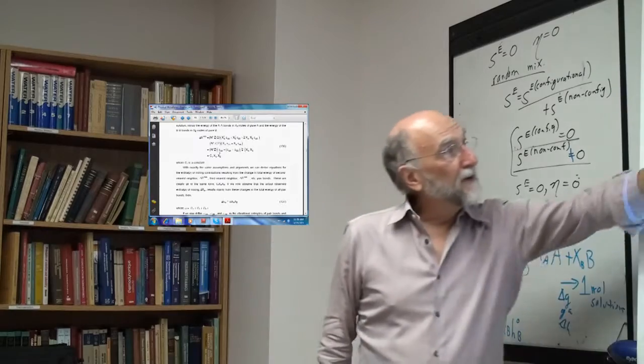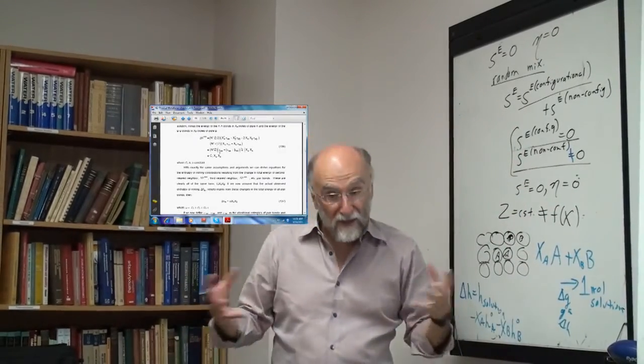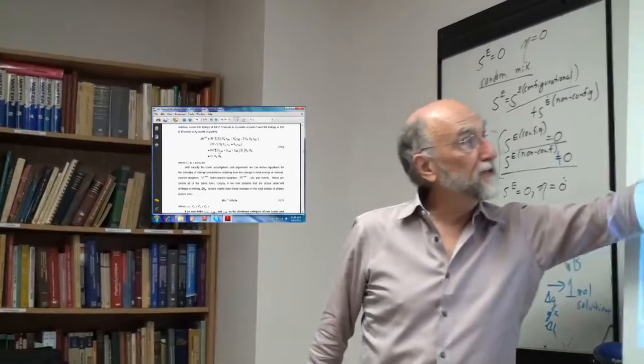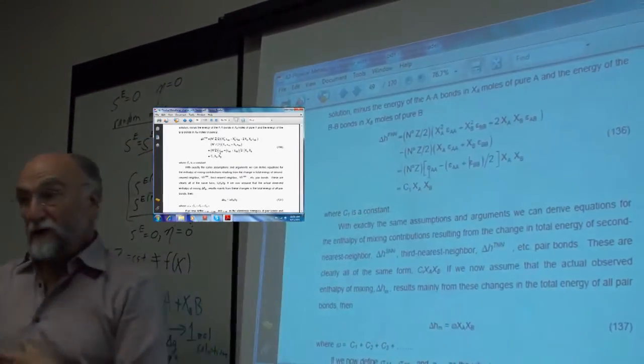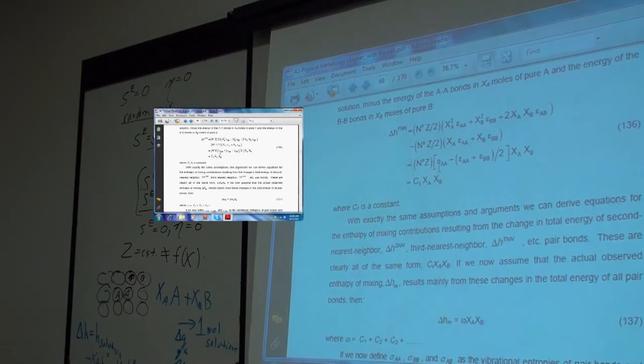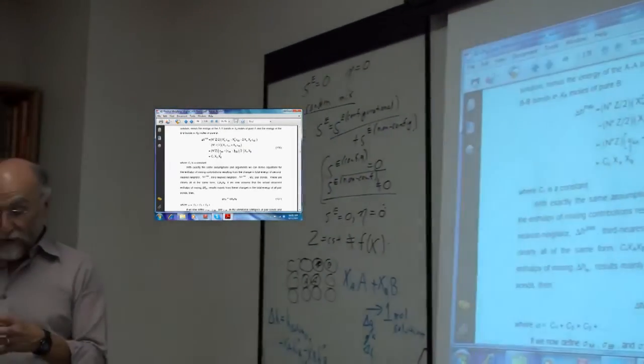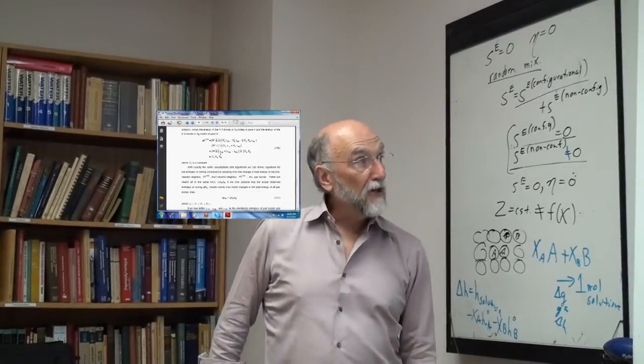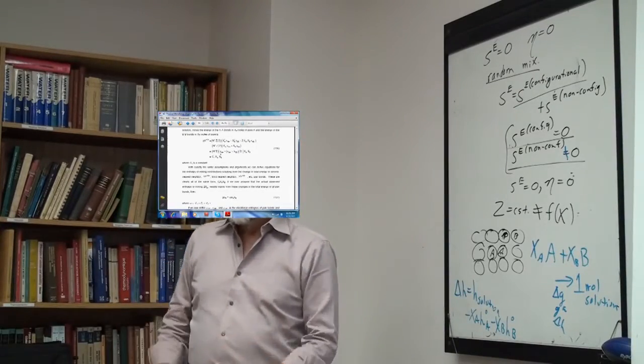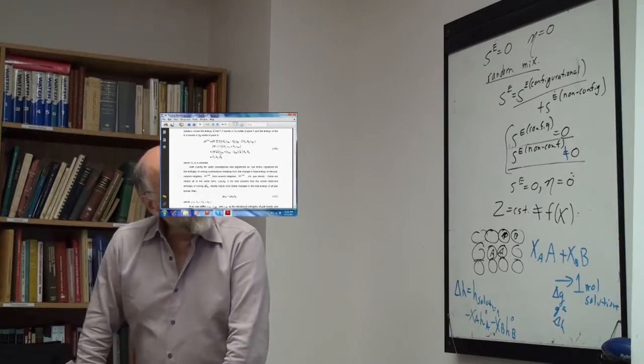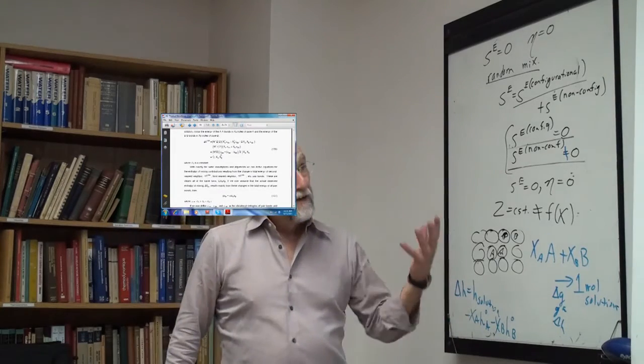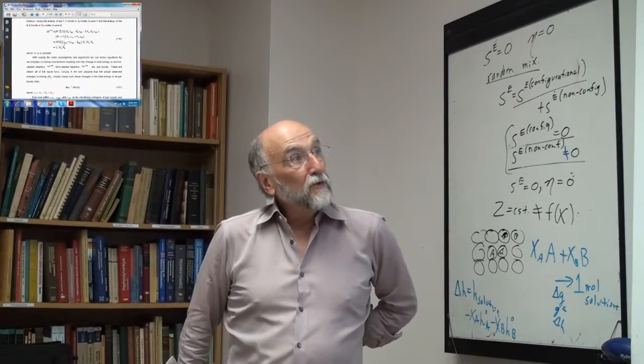So what the system really tries to do is it does get a certain amount of order. If delta H is negative, then you will find that the number of AB bonds actually is greater than in the ideal solution. If delta H is positive, then the number of AB bonds is less than the ideal number, and the number of AA and BB bonds is greater. So if the delta H is negative, because the AB bonds are stronger, you tend to have ordering: AB, AB, AB. If the delta H is positive, because the AB bonds are weaker, then you tend to have clustering. You tend to have A's clustering together and B's clustering together. If delta H is positive enough, of course, it'll separate into two solutions. Now what the system tries to do then, as I said, is find the distribution which minimizes G excess.